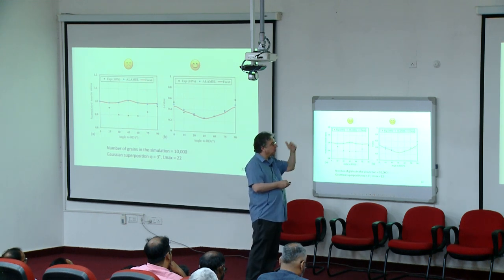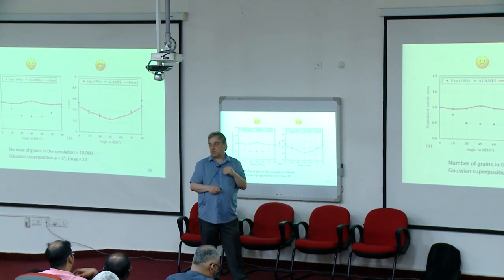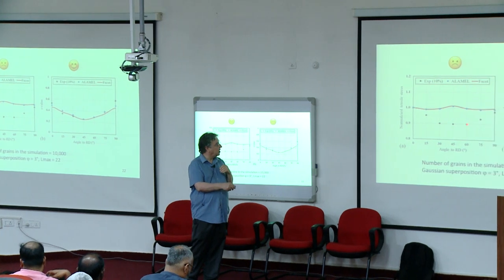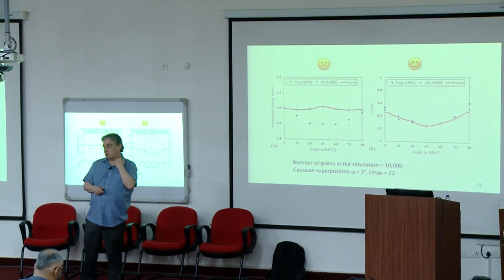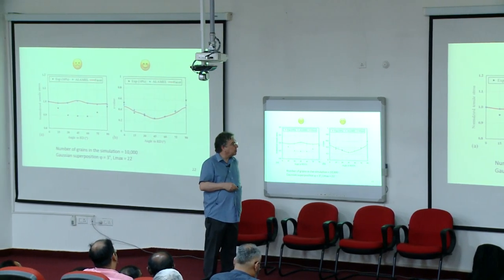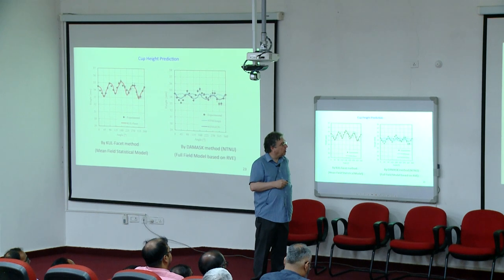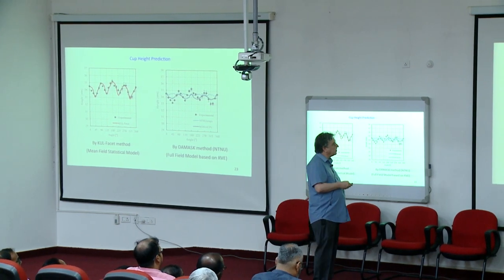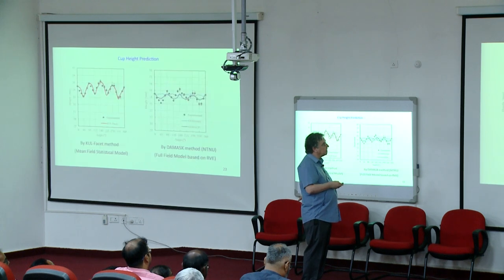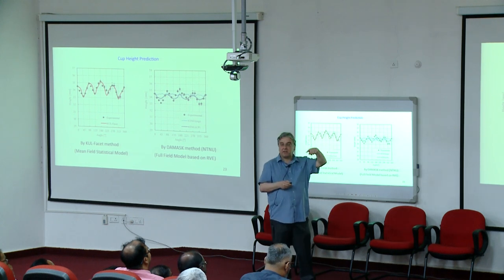However, it's not entirely all fun and happy, because the strength distribution, we don't get it very right. This is the yield strength evolution as a function of the angle with respect to the rolling direction, and you can see that it's not good. The prediction is not good. So there's still a lot of room for improvement, especially here. We try to do various things, and on the basis of this crystal plasticity method, we also try to model the cup heights, this cup earring.